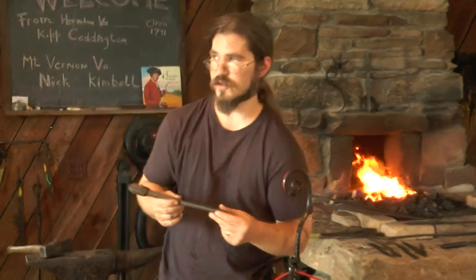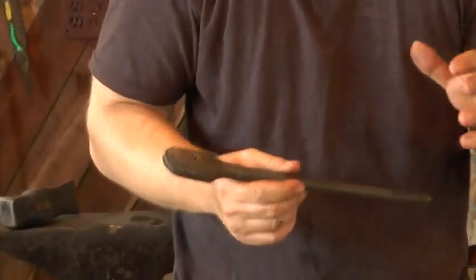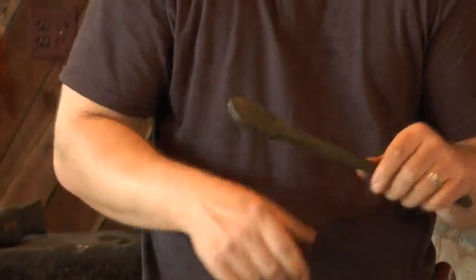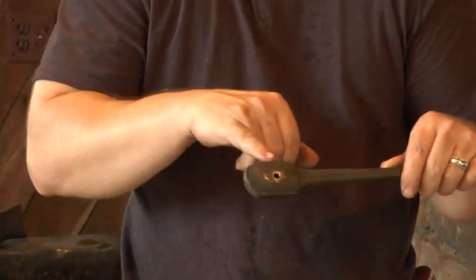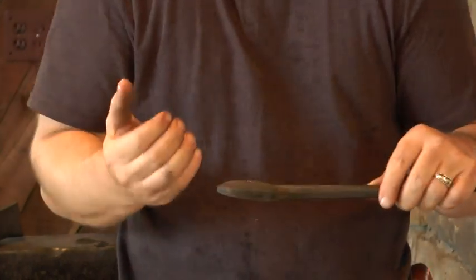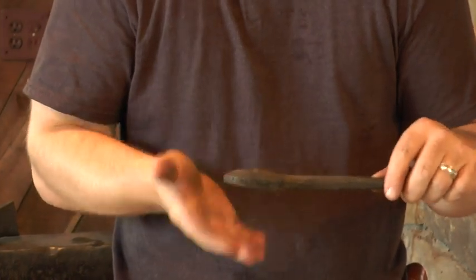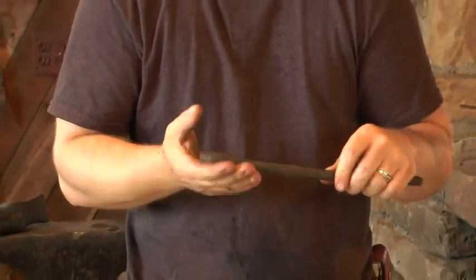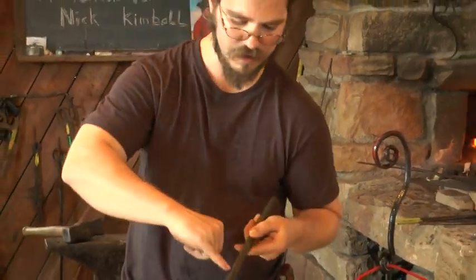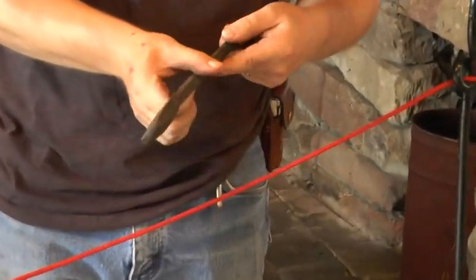So in the 18th century, they have steel, but it's expensive, and so you use it sparingly. The body of this tool right here is made out of wrought iron, and I just took a little bit of steel, and it's welded right onto the face here to give me a good impact surface, so it's going to hold its form while I'm heading the nail. But the iron is also going to absorb the shock to help prevent that steel from cracking and breaking. And so you can actually see along the corners here where that steel plate is resting on.